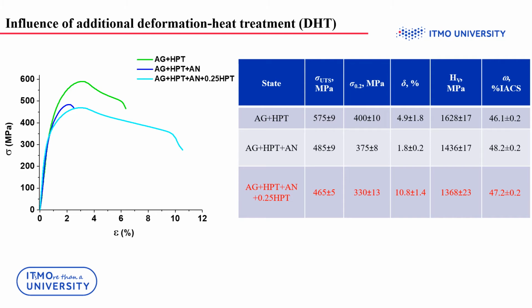However, we found that subsequent additional small HPT deformation by a quarter of a turn leads to a substantial increase in ductility, while the high level of strength is kept. Thus, we see that the proposed deformation heat treatment leads to a significant increase in ductility while maintaining high strength and reasonable electrical conductivity in the studied alloy.